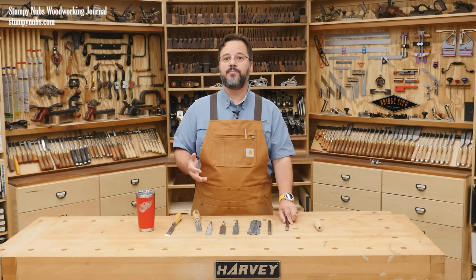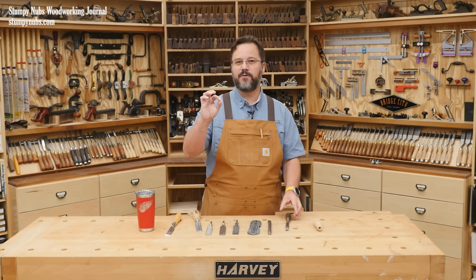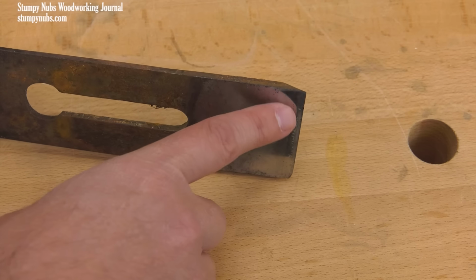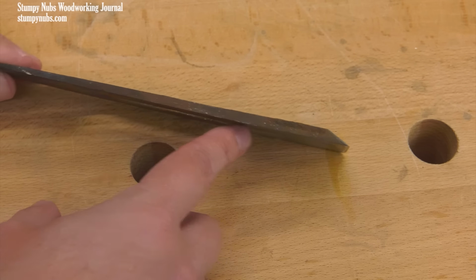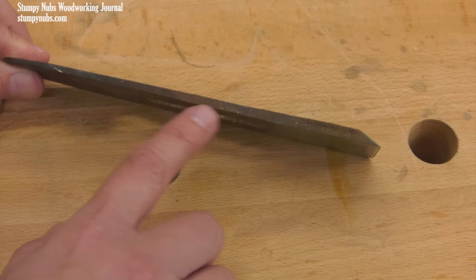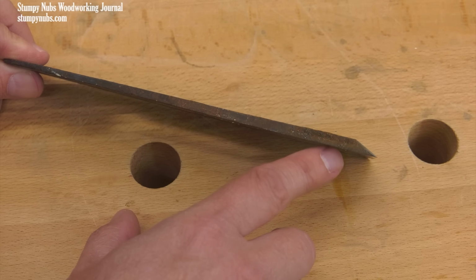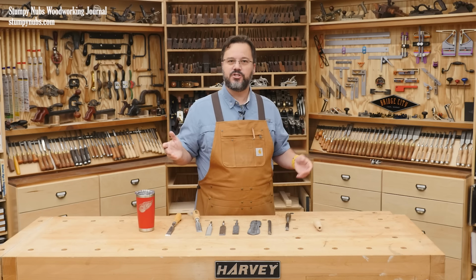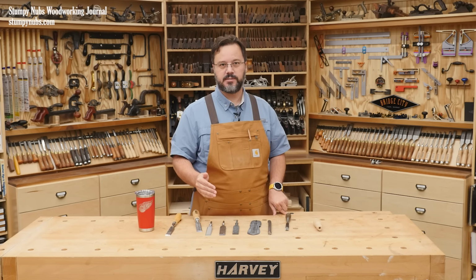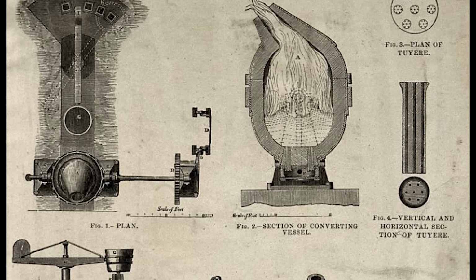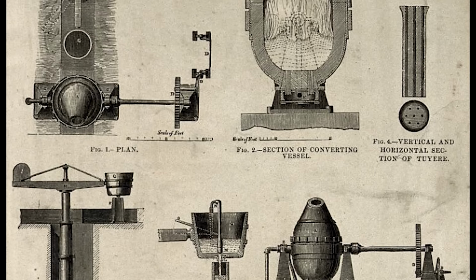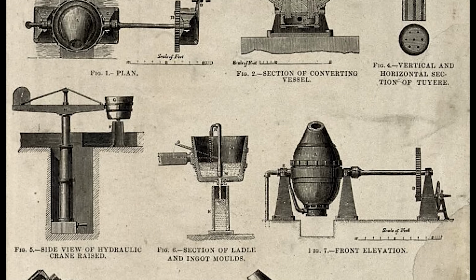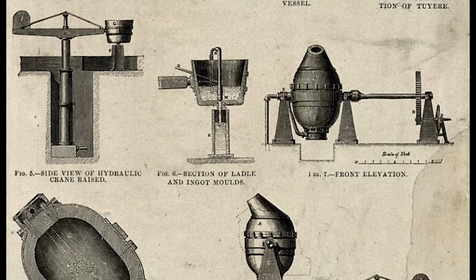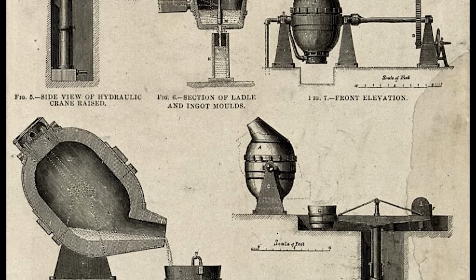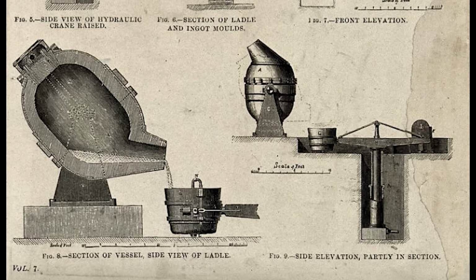In fact, it was common to forge weld a thin strip of good steel along the cutting edge of a wrought iron tool, such as this plane iron. You can see how it grows thicker near the bottom where the steel is attached to the iron. All that changed with the development of the Bessemer process. That involved blasting air into the molten metal to remove impurities through oxidation. It was faster and very large quantities could be produced at once, so tool steel became much less expensive.